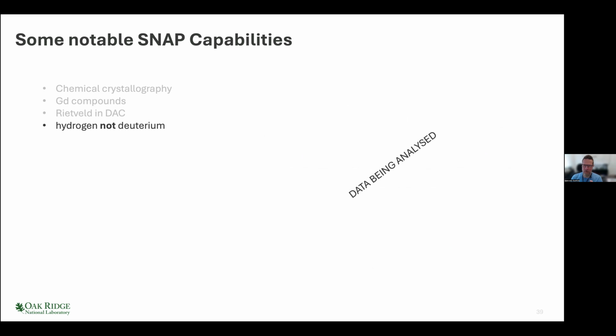And I don't have any data to show you because we're still analyzing this, but we've discovered that we can actually measure hydrogenous stuff instead of deuterium. In particular, if we look in a DAC, it turns out, for those who don't know, if you hit hydrogen with a neutron beam, you A, get huge absorption, you B, get massive multiple scattering, and C, you get a huge background. Turns out if you make your sample really, really small and really, really thin, most of that goes away.